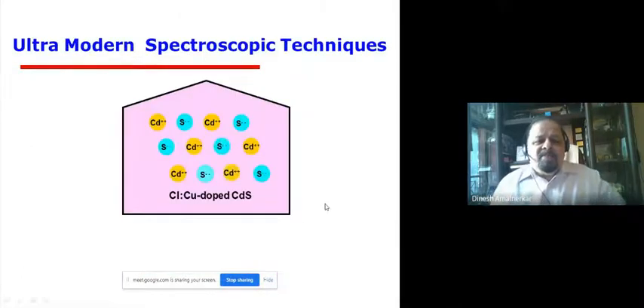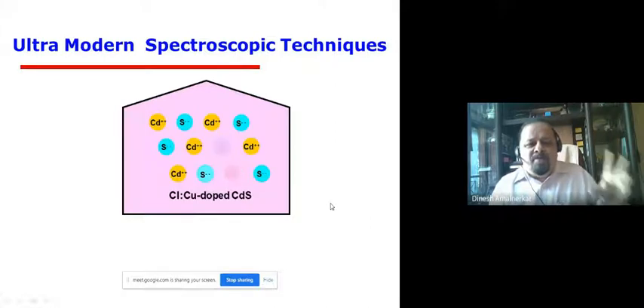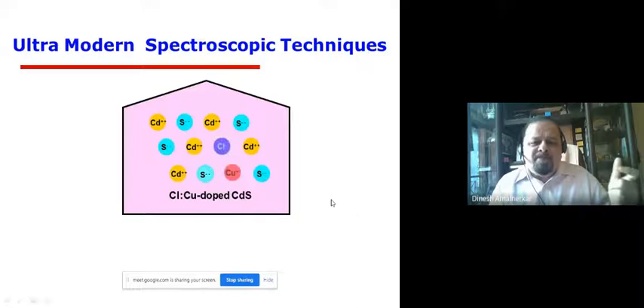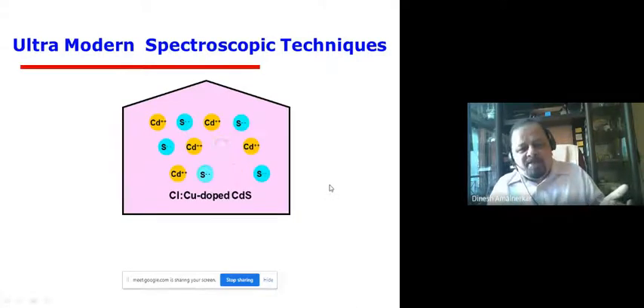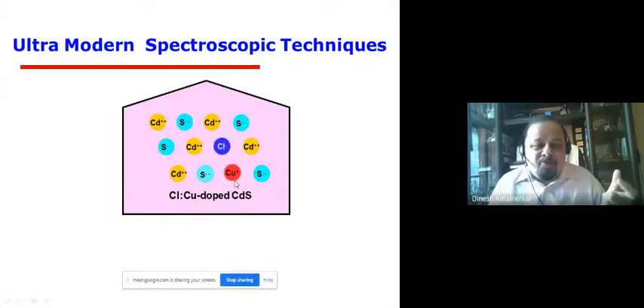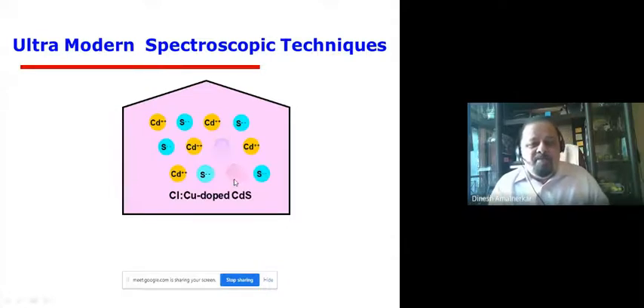Now, as I said earlier, cadmium sulfide contains two sublattices in pure state, that is Cd2+ and S2-. When we replace S2- by Cl- and Cd2+ by Cu+, that leads to a kind of sensitizing center here, which can contribute to photoconductivity, which we have seen earlier. But how do we know we are just getting Cu+ and not Cu2+? There's a likelihood that we may get Cu2+, but we presumed that we are just getting Cu+.